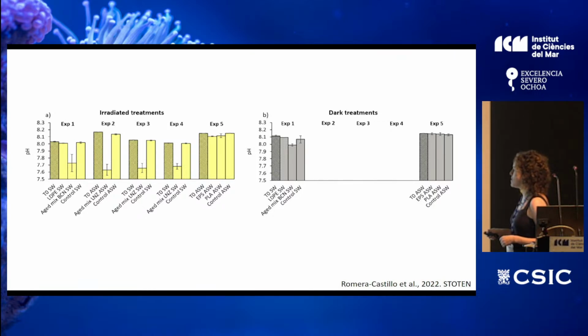Just in the EPS, the decrease was significant but very, very slight. And then in the dark, we see that there are no significant differences between the new plastic treatments, EPS and PLA, with the control and the time zero. And in this experiment, we just saw a difference with the aged plastic, that even in the dark, decreased the pH a little bit.